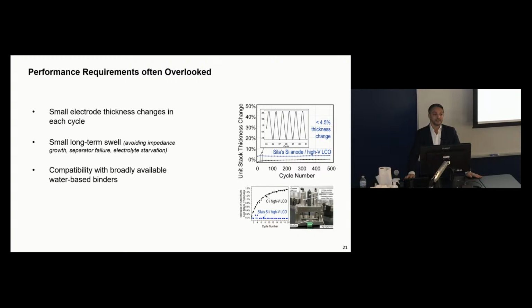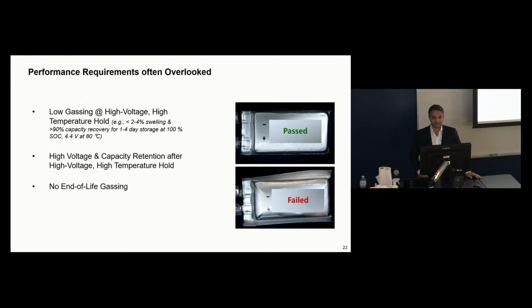In addition, when the materials are processed in lithium-ion battery facilities, the current requirement is to reduce CO2, reduce emissions, reduce the use of harmful chemicals. So you have to make sure your technology, your particles in our case, would be compatible with the best technology on the market, in this case, water-based electrode processing. And so Sila had to overcome it. And in fact, the performance of high-performance batteries with silicon anodes is actually better than high-performance batteries with otherwise analogous, but with graphite anodes. Smaller swell, better performance.